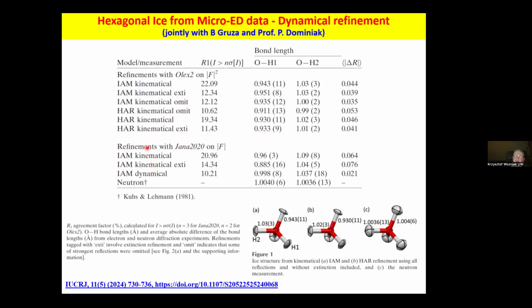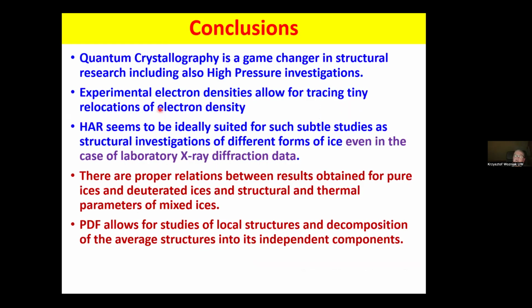However, what really matters is performing dynamical refinement of the data, because the dynamical refinement gave us values which are almost exactly the same as those from neutron refinement. So in conclusion, quantum crystallography is, in my opinion, a game changer in structural research, including also high pressure investigations. Experimental electron densities allow for tracing tiny relocations of electron density. Hirshfeld atom refinement seems to be ideally suited for such subtle studies as structural investigations of different forms of ice, even in the case of laboratory X-ray diffraction data.